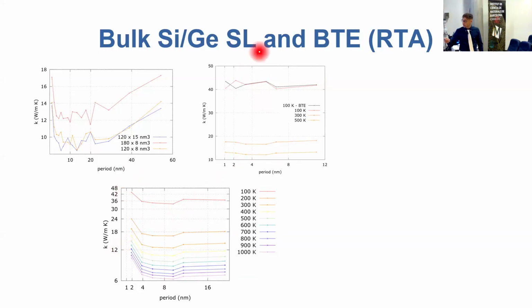And you can see that in the two cases, there is always a clear minimum in the thermal conductivity, except for the 100 crystal direction at 100 Kelvin, where we also repeated the simulation batch, avoiding the approximation, but still no minimum appeared. We assumed that this must result from some quantum effect, which becomes dominant at low temperature, which is not captured by our formalism.